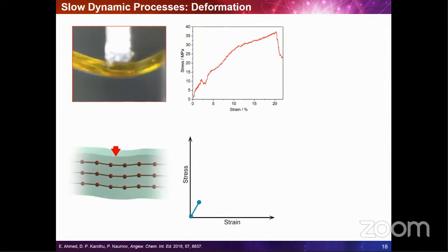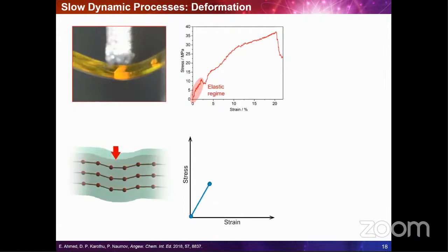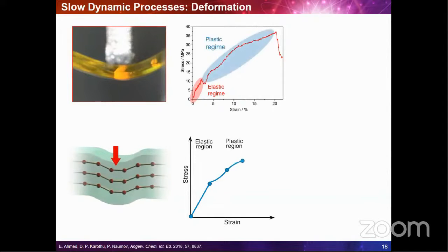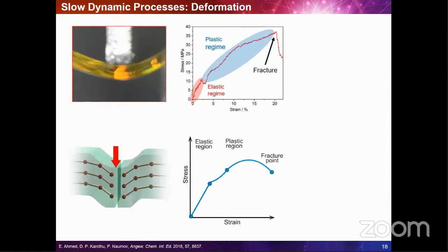So just to give you a one-on-one introduction to mechanical testing or deformation of crystals, well, if you go with the classical mechanical principles, whenever you apply stress on a solid object, the object will initially undergo elastic or reversible deformation, and this is followed by plastic or irreversible deformation. And this goes on until you induce a fracture, and then the crystal or object will break. For small stresses, basically, this stress-strain curve, initially, as you can see from this plot, is linear, and this follows Hooke's law. And you can estimate, not really determine, but estimate the elastic modulus of the material from this elastic regime as a measure of its stiffness.